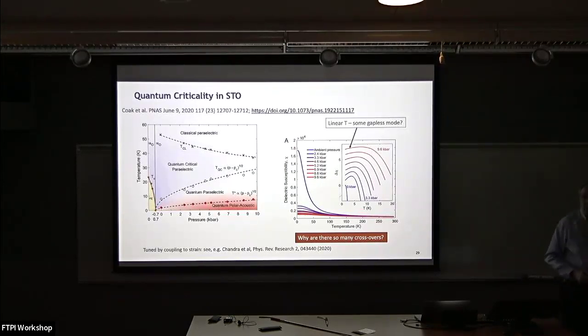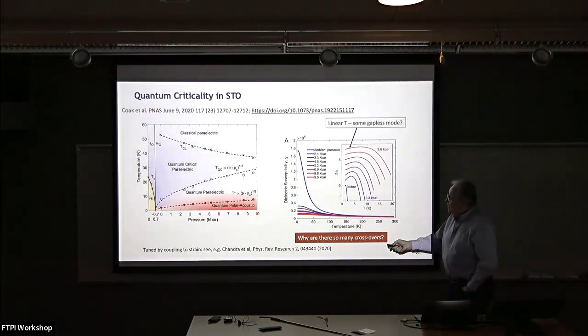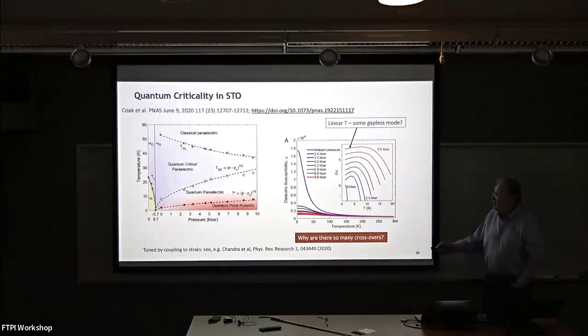I think some of them Premium may talk about later today, because we're fairly sure what the physical origin of these is. But the odd thing about them is that there are several. More than one might have expected. You can actually go along the other axis. You do that by going to oxygen 18. And oxygen 18 does actually form a state. You can also make the system ferroelectric by doping with the right kinds of things. And you see that too. But there's a sort of generic phase diagram.